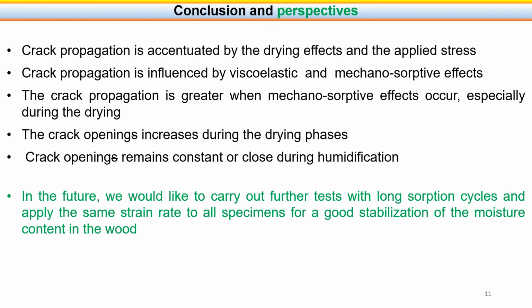In conclusion, we can see that crack propagation is accentuated by the drying effect and the applied stress. Crack propagation is influenced by visco and mechanosorptive effects. The crack propagation is greater when the mechanosorptive effect occurs, especially during the drying phase. The crack opening increases during the drying phase. Crack opening remains constant or closes during humidification.